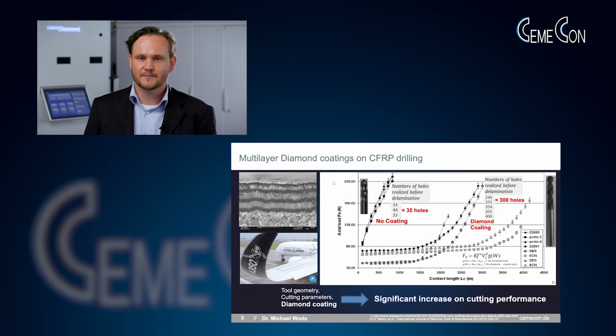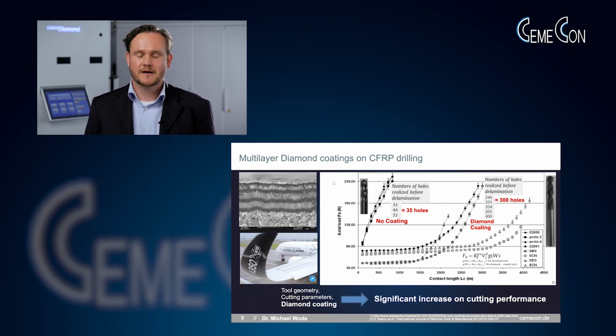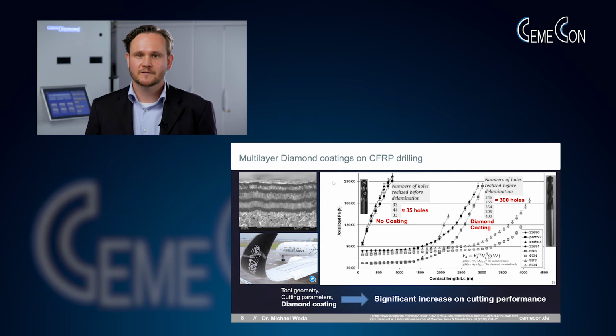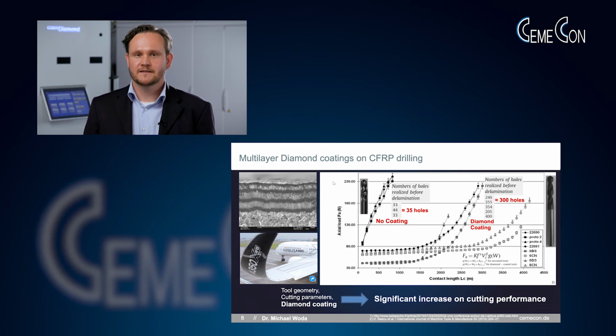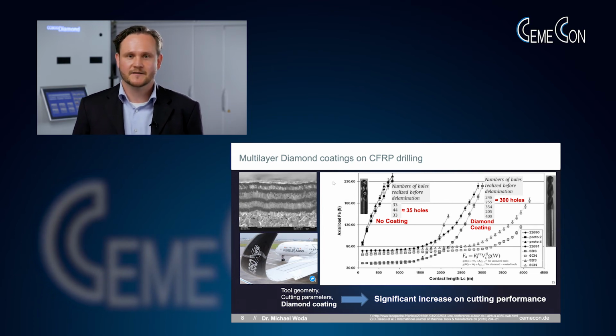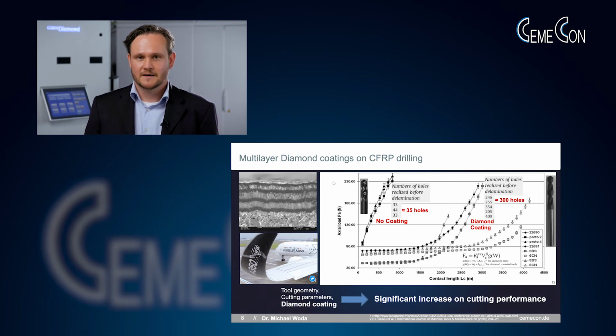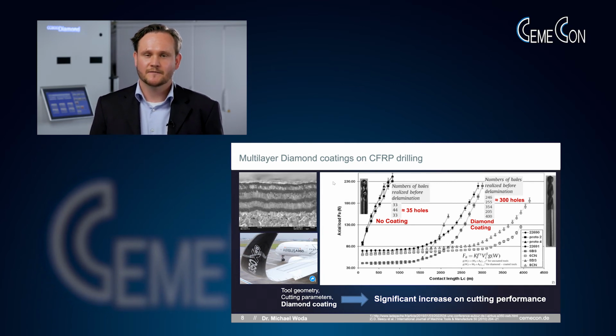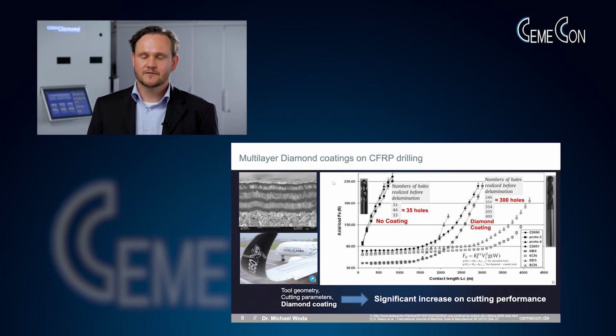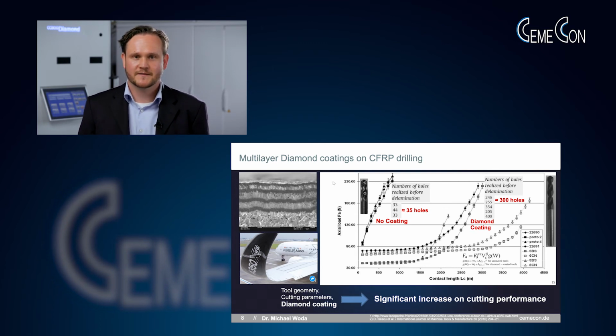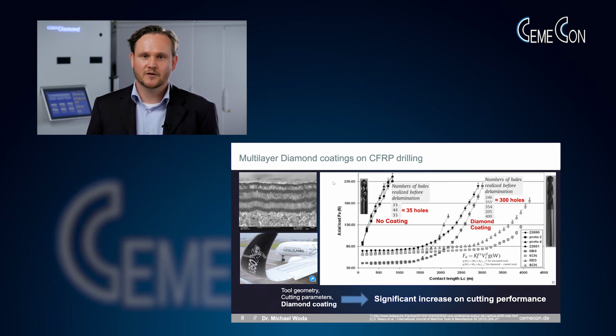We start with a case example in the modern aerospace industry, where we are interested in drilling carbon fiber reinforced plastic materials. Here in this plot we can see the results of such an experiment. We have shown the axial load which is measured on the tool versus the cutting path. We know that the onset of the increasing behavior is directly correlated to the tool life of the cutting tool. Here we can unravel the clear benefit of the multilayer diamond coatings, as we have an increase of about a factor of 8 when we compare the uncoated reference to the diamond coated cutting tool.